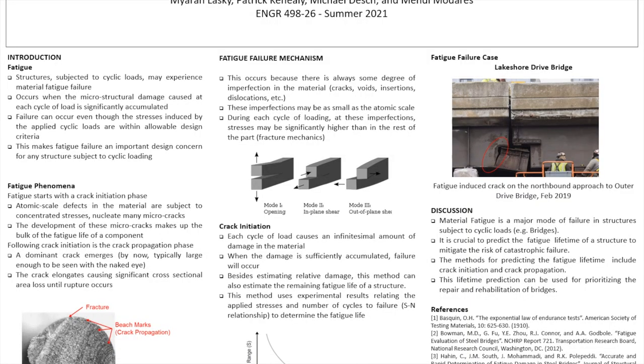Structural fatigue failure prediction. Fatigue is a mechanism that occurs due to cyclic loading, oftentimes at loads within allowable design criteria. Microstructural damage occurs with each cycle, and when enough damage accumulates, fatigue failure occurs. This makes fatigue an important consideration for any structure subject to cyclic loading. The fatigue phenomenon starts with crack initiation. Crack initiation occurs at an atomic level around defects in the material.